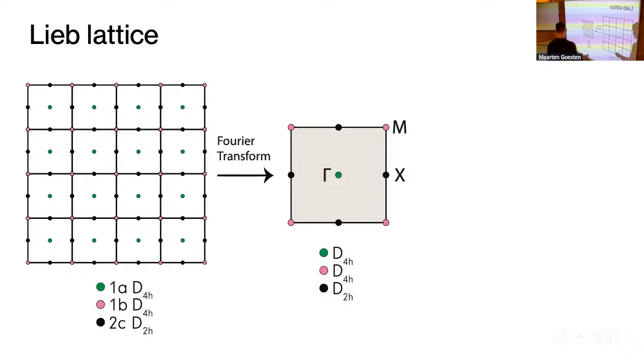Any crystal structure you can describe as a collection of Wyckoff points, where every different Wyckoff point gives you a different site symmetry. If you take the three Wyckoff points here, point 1a is fixed, stabilized, mapped onto itself by all operations of the D4h point group. This point group contains fourfold rotation and a horizontal reflection plane. If you take this green point here and do a fourfold rotation, you see that you get the same back. Same for this pink point here, which is another Wyckoff position. But if you take, for instance, the black point there, then you see that your fourfold rotation gives you something different in return. So this is a different Wyckoff position, which actually has locally D2h symmetry.